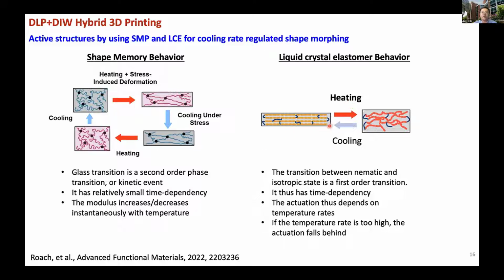But if you look at liquid crystal elastomer, you really have a phase transition, because we have a liquid crystal phase at room temperature. As you heat it up, the liquid crystal phase becomes not aligned, so they become randomly distributed and you become isotropic. So you do have an aligned phase and also a random phase, so it is a phase transition process. It's a first order transition, and we know that a first order phase transition has very strong time dependency, right? For example, if you try to freeze water, the water will not freeze immediately. You have to put it at a temperature below 0 degrees C for a certain time for the water to become ice. Similarly here, it is a time-dependent process.